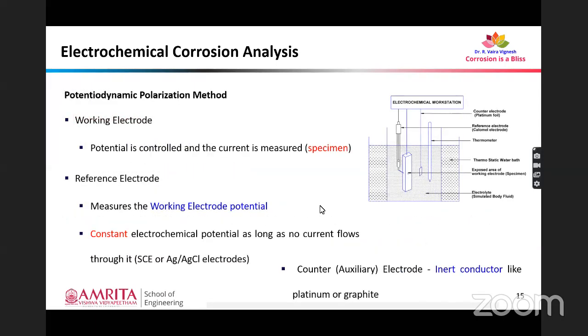And coming towards the working methodology of this potentiodynamic polarization method, what we do is we take the working electrode and place that inside the container that has the electrolyte solution. If we want to check for materials that have to be in marine environments, we generally use 3.5% NaCl solution, that is mimicking the seawater environment.